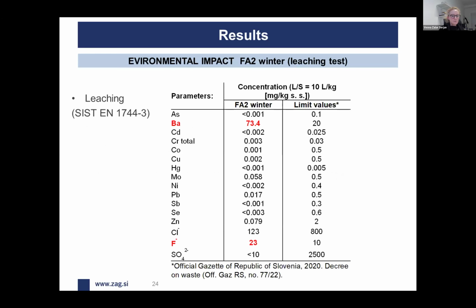Of course, one very important thing when you decide to use or try to check whether some industrial byproduct material can be used or cannot be used is environmental impact. So we performed the leaching test according to Slovenian legislation for FA2 winter S, which was chosen for further investigation. And the results showed that concentrations of barium and fluorine exceeded the limiting values.